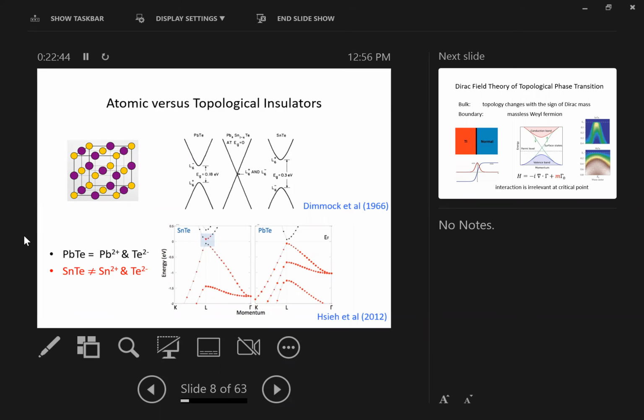But there's something more we did. We looked at the wave function of these states in momentum space. The size of the red dots labels the weight of the electron wave function on the tellurium atom. So if you look at lead telluride, you see that all the occupied states below the Fermi level are coming from tellurium, the p orbital of tellurium.